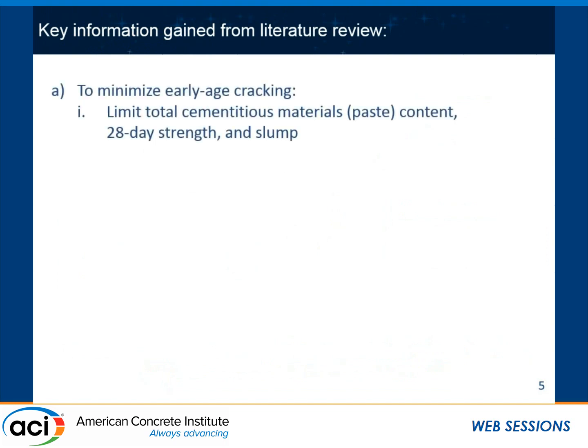Okay, so some of the key information gained from the literature review. One is that to minimize early age cracking, we have to limit the total amount of cementitious materials or paste content, 28-day strength, which has a large impact on the stiffness of concrete, as well as slump. And there has been good work, including the very good work at the University of Kansas, that shows that higher slump concrete could be more prone to things like settlement cracking and so on, or excessive slump in concrete.